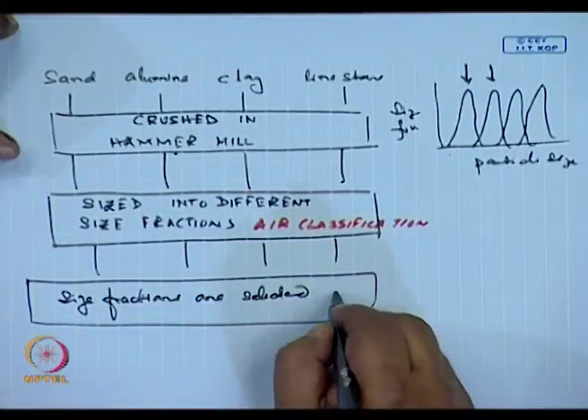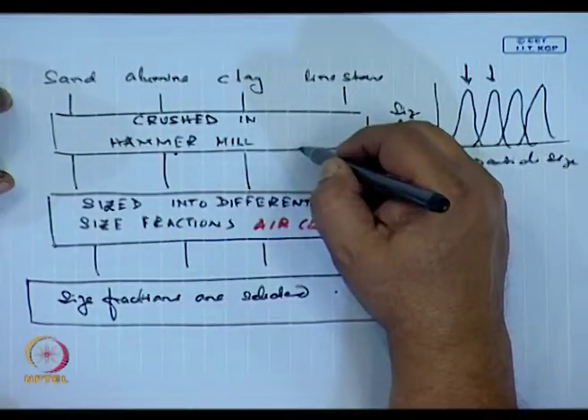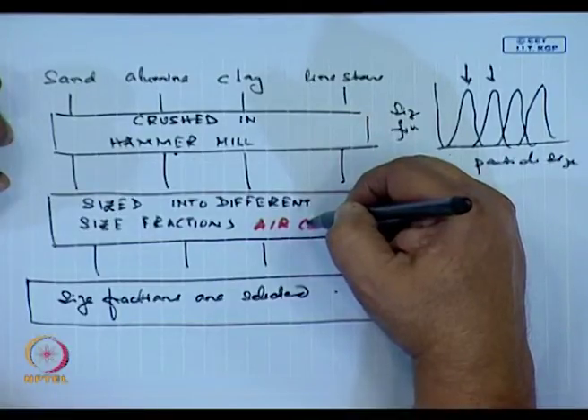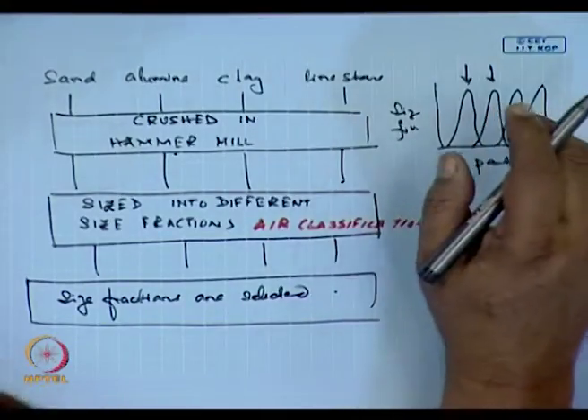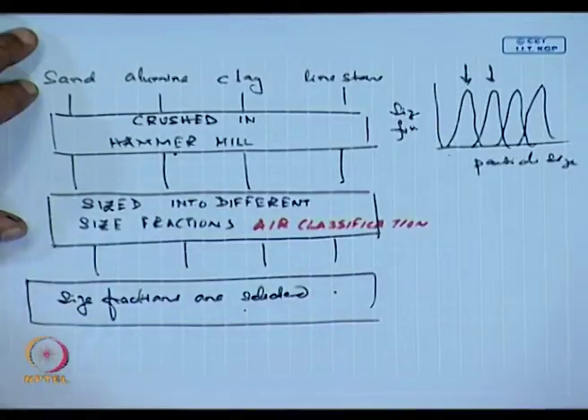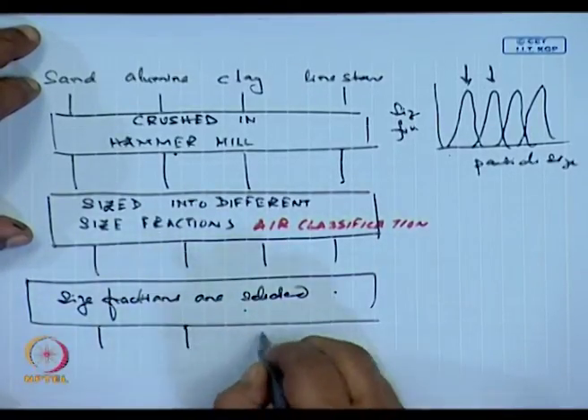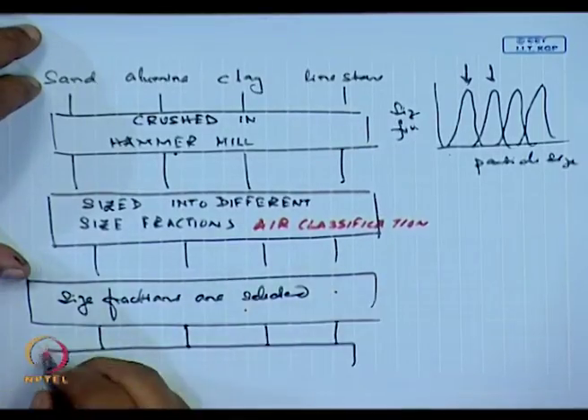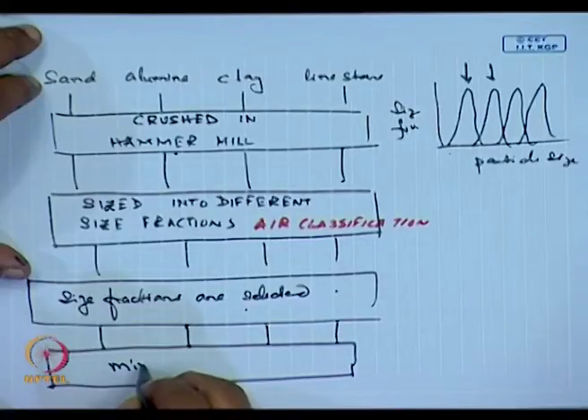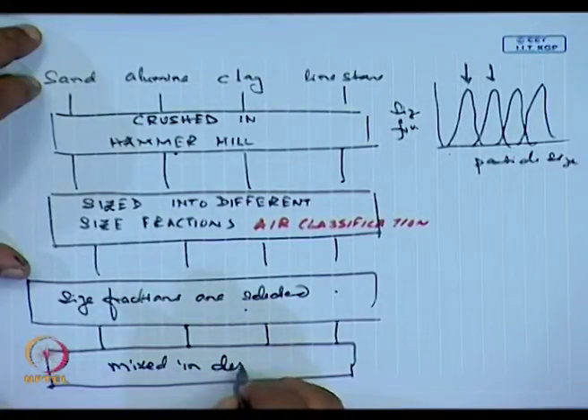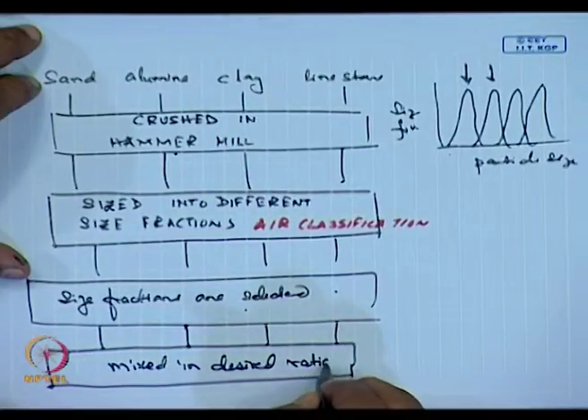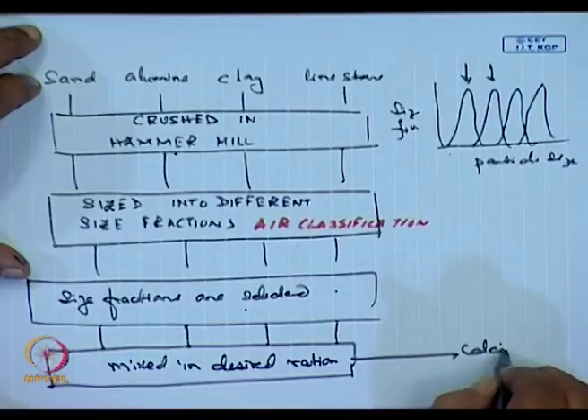Now all you have to remember here is that from the hammer mill all the powder is being fed into the air classification system by high velocity air, and the powder which is collected from here is again picked up by air in a closed circuit. So, these size fractions are selected and then mixed in desired ratio and fed to the calciner.